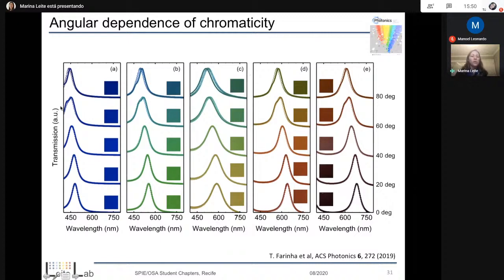What you're seeing here is transmission as a function of wavelength. The dots are experiments, and the solid line is calculation. These little squares are real color photographs. We simply cropped the photographs, but there is no manipulation at all. At 0 degrees, you read these graphs bottom to top. It's normal incidence. You can see that the blue is maintained, a very strong blue hue, up to 80 degrees. For the green sample, it changes a little to a petroleum type of blue. The Dijon one changes to a greenish. But overall, I would say that up to almost 40 degrees, it's quite robust, and the colors are very vivid.